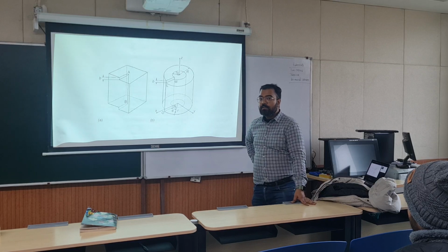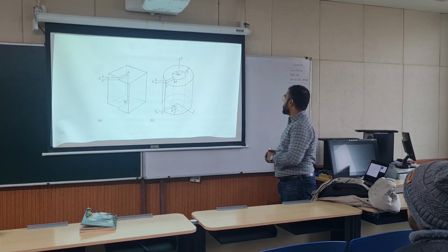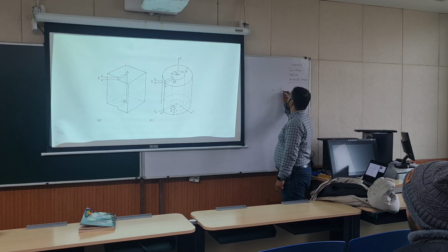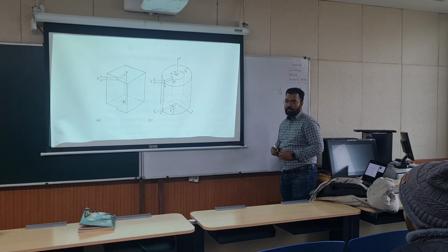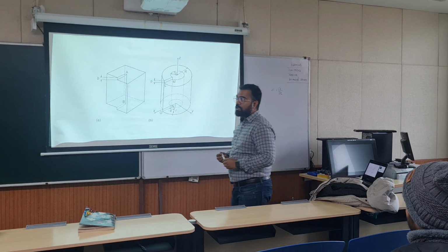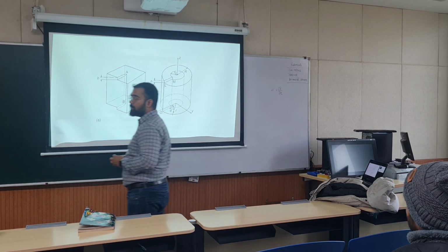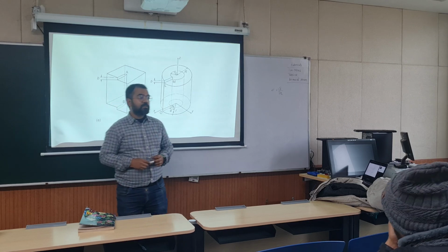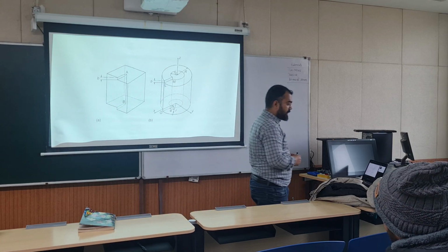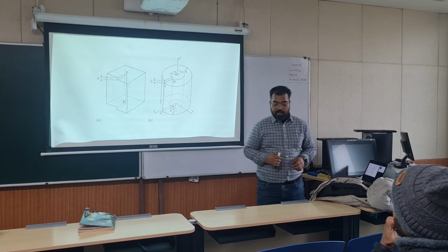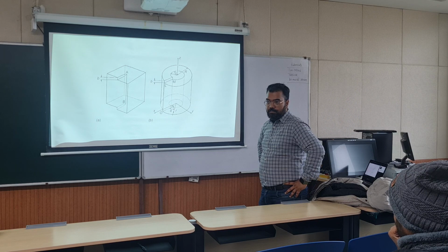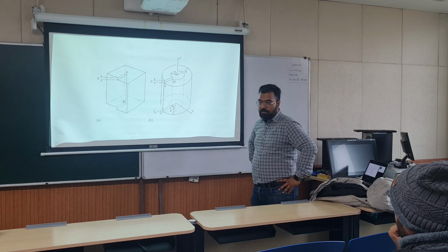This is called the theoretical strength of the material, and that comes out to be G by 2 pi. Okay, so this is a very high amount. G of the order of 60 gigapascals will give you a strength of 10 gigapascal, and no material shows 10 gigapascal. So then we came to the understanding that things happen in a stepwise manner, right? And what are those steps?